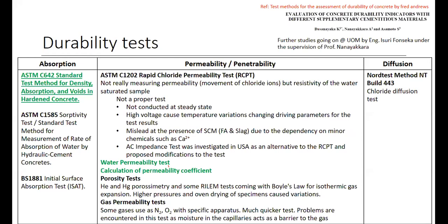And there are other techniques that we can utilize to measure the permeability or the penetrability. Here, the most popular test is ASTM C1202, the rapid chloride permeability test, usually called RCPT. Actually, in our tests also, and not only us but researchers all over the world, have identified that this is actually not a permeability test. It's actually measuring the resistivity of the saturated sample, but it's not the proper mechanism to identify durability. Even though we are utilizing it, it's not the correct test.